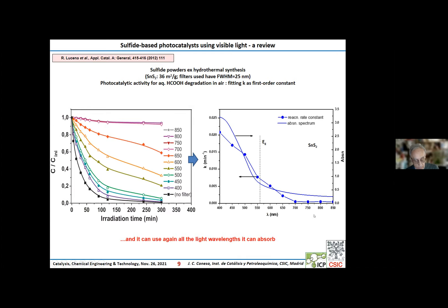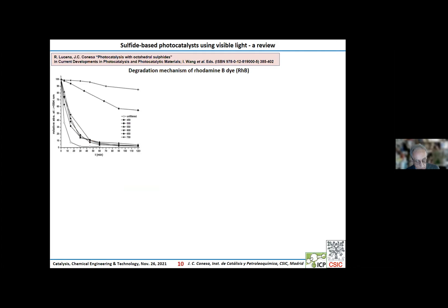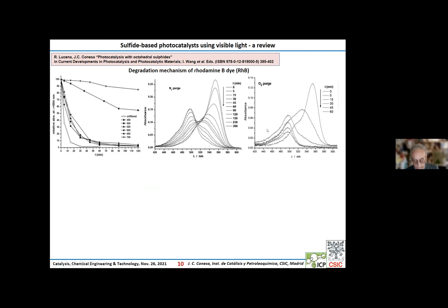Let's see now what we can learn about the degradation mechanism of the rhodamine B dye when using tin sulfide. If we check the rate at which it is degraded with different filters and monitor the 554 nanometer wavelength, there is an interesting result. When comparing results under nitrogen and oxygen bubbling, we see clear differences. Furthermore, in both cases there are no isosbestic points, which means there are at least three components in the degradation process.